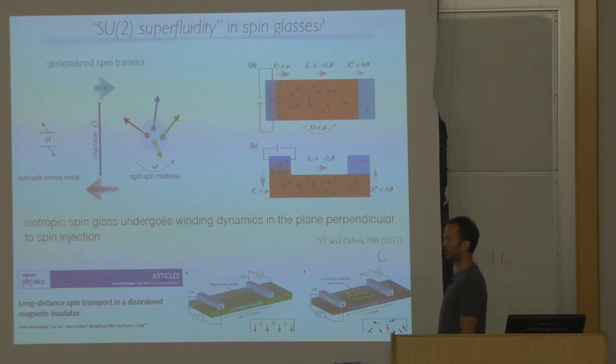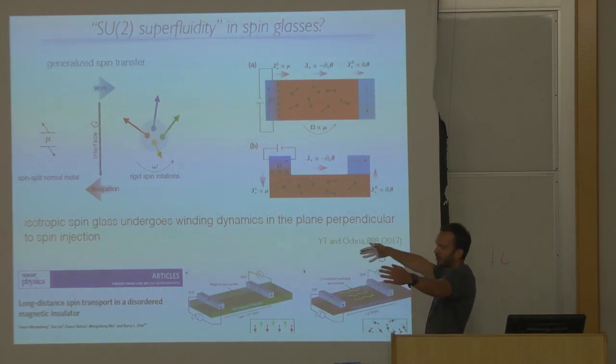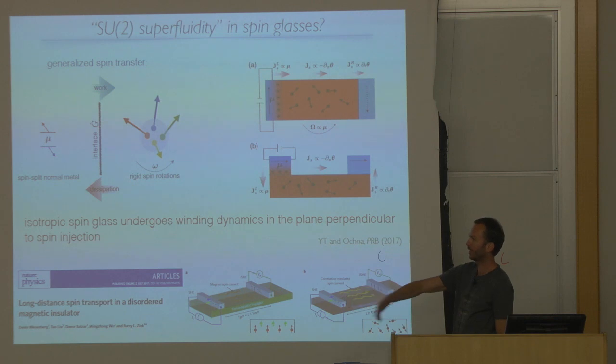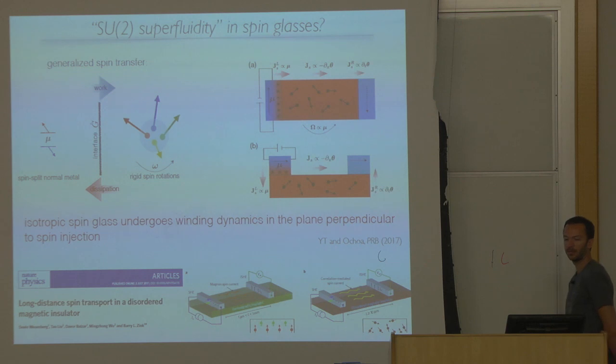a diffusive process in which instead of creating this winding, you create just localized spin excitations which propagate, and the spin excitation can simply disappear. Like in your experiments, as you know, the process is diffusive, so there is some diffusion length beyond which the signals decay exponentially. In our case, even in the presence of damping, the signals are algebraically long-ranged. And the damping is just a practical matter in the end. We can estimate for which sizes damping becomes important, for which sizes it's not so important. But it is an important practical matter, not so fundamentally of a concern.